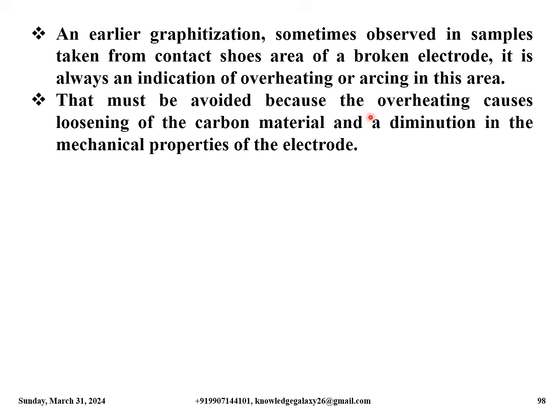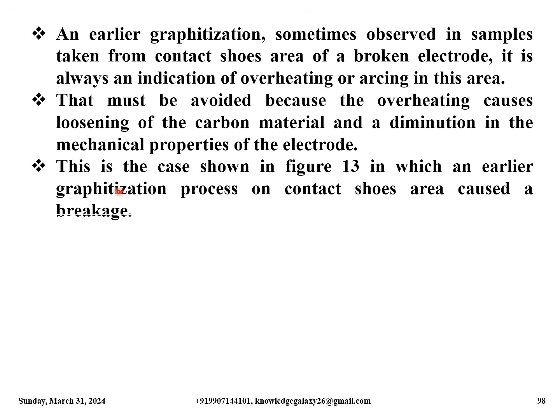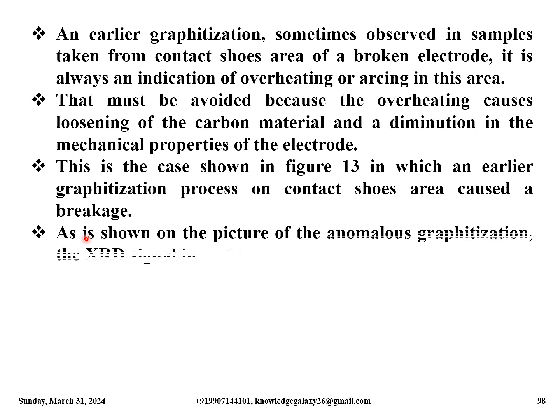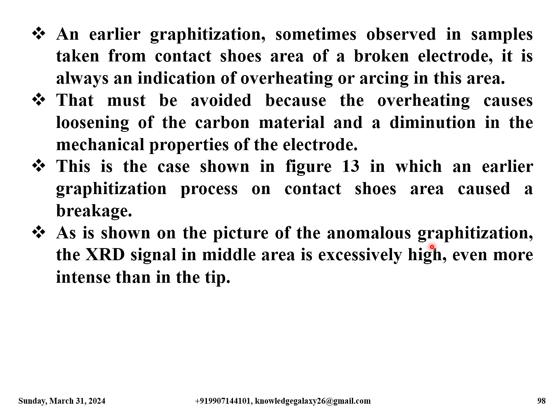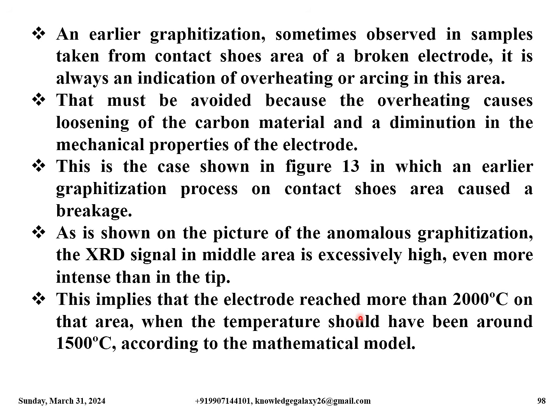That must be avoided because the overheating causes loosening of the carbon material and a diminution in the mechanical properties of the electrode. This is the case shown in figure 13, in which an earlier graphitization process on the contact shoes areas caused a breakage. As shown in the picture of the anomalous graphitization in previous slides, the XRD signal in the middle area is excessively high, even more intense than in the tip. This implies that the electrode reached more than 2000 degrees Celsius in that area when the temperature should have been around 1500 degrees Celsius according to the mathematical model.